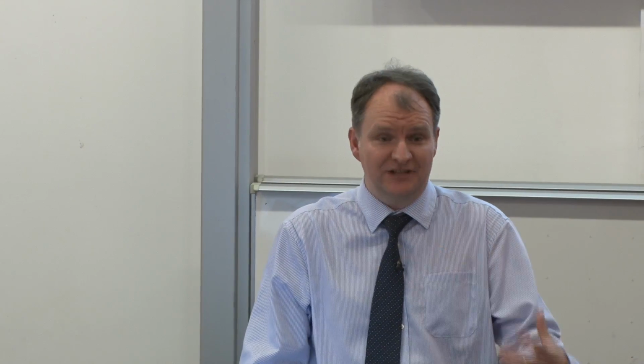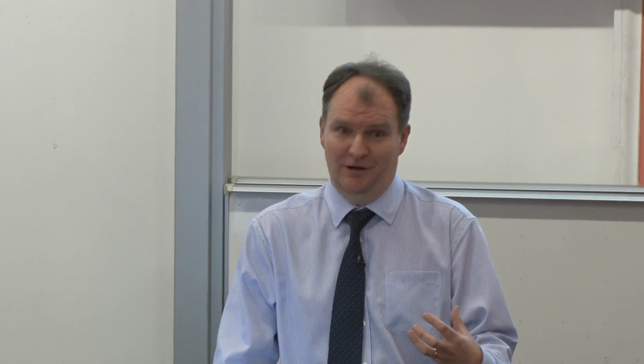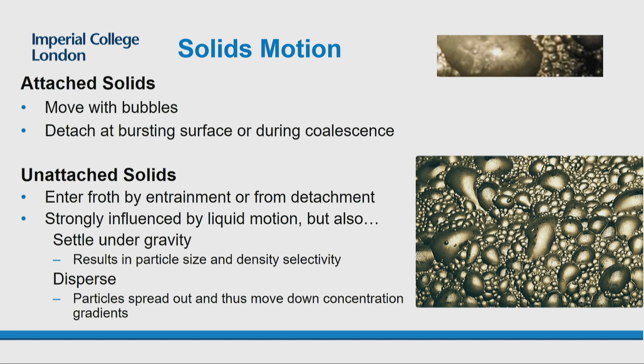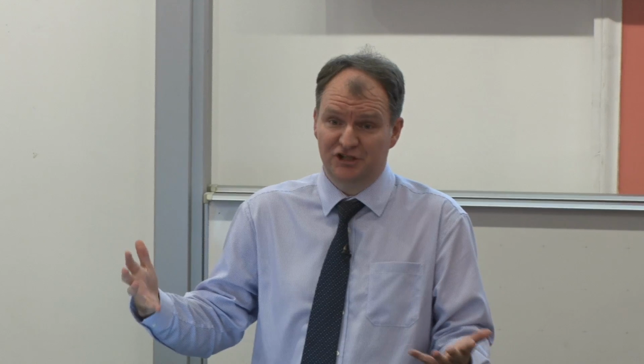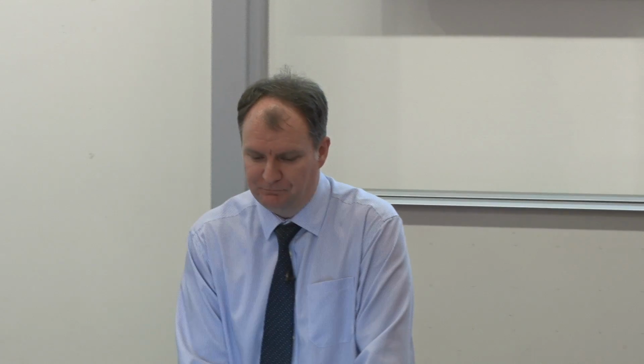So the final thing I needed to add to the models to be able to predict the behavior of a flotation froth is a model for the solid behavior. There are two main types of solids we need to account for. There are those solids which are attached to the bubbles, and that's hopefully the valuable material, and they'll just move with the bubbles. So you know their velocities if you know the velocities of the bubbles. The complexity with them is that as you get coalescence and bursting, they become detached. And so you end up effectively dropping particles off the surface of your bubbles and into these plateau borders that you now need to model.